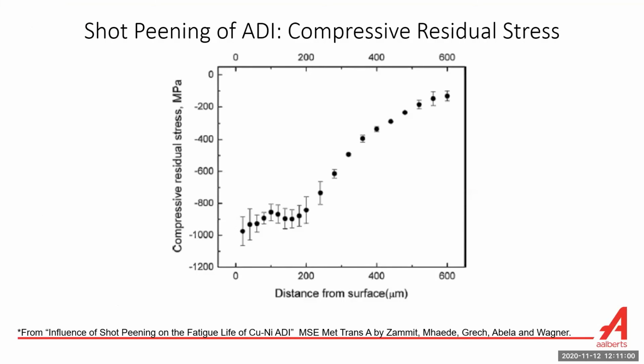And then if you shot peen ADI, you can put a significant residual compressive stress on the surface that is also due to this phase transformation.